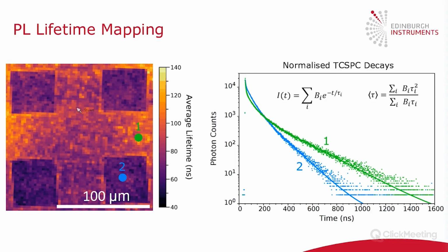And if I show that, again, you can extract the lifetimes from each point. Here what we did was we measured the PL decays at every point on this map, and then fitted these decays with multi-component exponentials, and then calculated the average lifetime to get this color plot here. This shows that in regions where the carbon nanotubes are present, the lifetime decreases, compared to the bulk sample, when you're on top of the carbon nanotube. And this is what we would expect if we're getting hole extraction, because if holes are being pulled from the perovskite, then they can't emit photoluminescence, and the lifetime should therefore decrease. So this gives complementary information to our confocal intensity imaging, that these carbon nanotubes are acting as hole extraction layers in the perovskite.